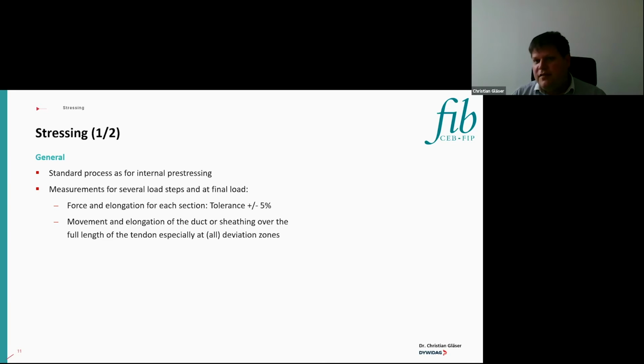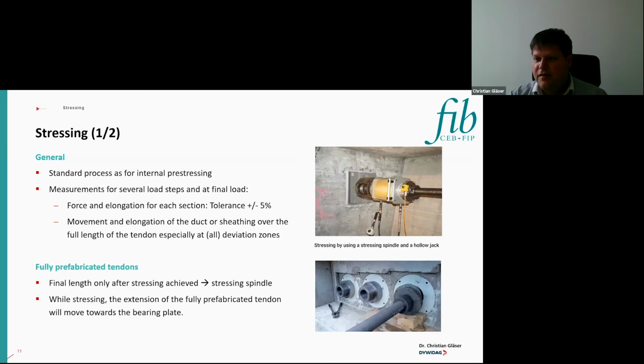So the standard process is quite similar to what we know for internal pre-stressing. So we also make measurements during the stressing at several load steps and at the final load, like force and elongation. But what is additional and quite recommended is also measuring the movement and the elongation of the duct or sheathing over the full length, especially at the deviation zones, to really see if there is any, let's say, untypical movement, and that should of course then be identified if this is happening.